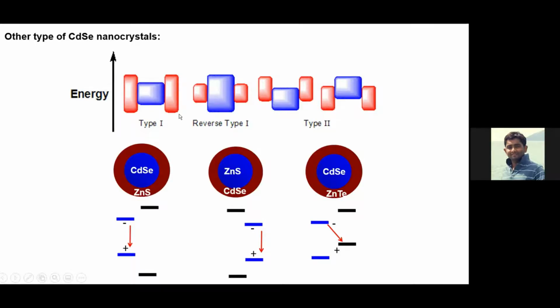Now it is reverse type 1. That means you have an inner core material with a higher band gap, and the shell material has a smaller band gap. So you can make a quantum well by using reverse type 1. That means you have zinc sulfide here, cadmium selenide there, and you can cover with another zinc sulfide. So you will have a squeeze of the exciton, meaning your electron is in the well. That's why you can get the quantum well structure from reverse type 1.